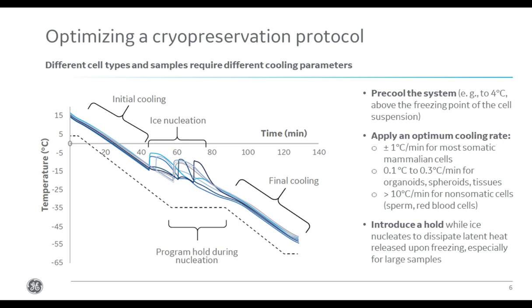Now we've covered some of the science, how do you go about optimizing your own protocol? Firstly, we would advise deciding the starting temperature of your process. This should be as low as possible, but above the freezing point of the solution. Normally, the cryoprotectant is added to the cells, and then the cooling process started no higher than about 4 degrees. It's important when starting the cryopreservation process to make sure the controlled rate freezer is at 4 degrees before you begin. The cooling rate will vary depending on the cells, and it's imperative to optimize this for each cell type of interest. However, 1 degree a minute is a good starting point to optimize the cooling rate if you can find no papers in the literature for the cell type you're interested in.